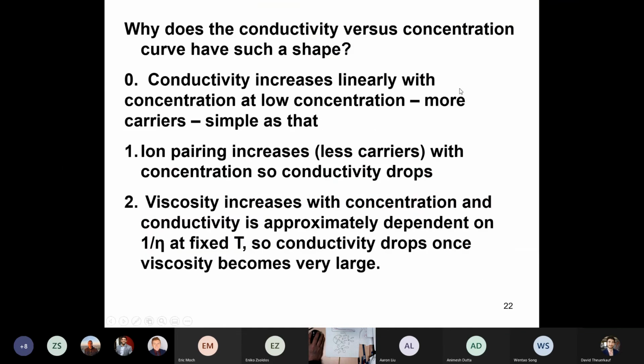Here we go. And then finally, another reason why the conductivity decreases at high concentration is the viscosity of the solution increases with concentration. And the conductivity is approximately dependent on 1 over the viscosity at fixed temperature. So the conductivity drops once the viscosity becomes very large.